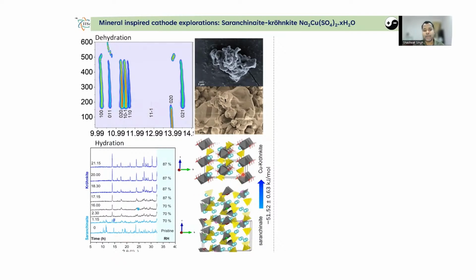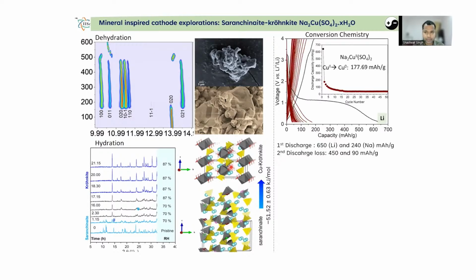The high structural reversibility comes from the structure. As you can see here, initially in the hydrated phase, there's a hydrogen-bonding based glue which holds the structure together. However, once this glue is removed, the structure breaks down. Further problems come from the Jahn-Teller distortion of copper, which makes the dehydrated compound very low in symmetry. Because of the absence of any migration pathway, insertion chemistry could not be tested.